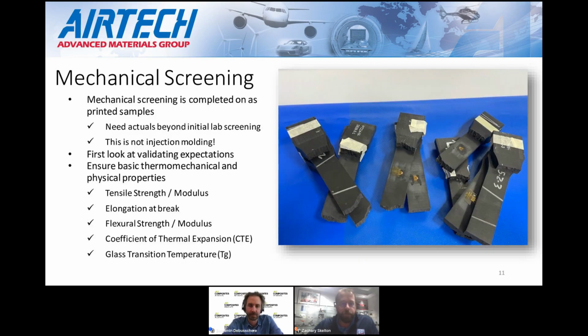So post-print trials, we'll look at mechanical screening. So really everything is done with the intent of as printed, right? So you can see several of the coupons there. But this is not injection molding. In reality, the injection molding properties really don't do anybody any favors. But we're going to start looking at things like tensile strength and modulus, elongation at break, flexural strength and modulus, CTE, as well as glass transition temperature. Again, just making sure that it is meeting the expectations.